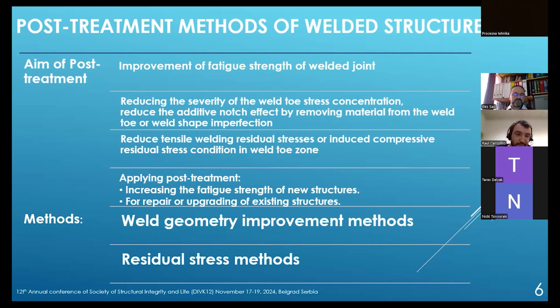The other approach, where we also apply post-treatments, is the residual stress reduction methods, where the target is to induce compressive residual stresses in the weld toe zones by applying different methods.